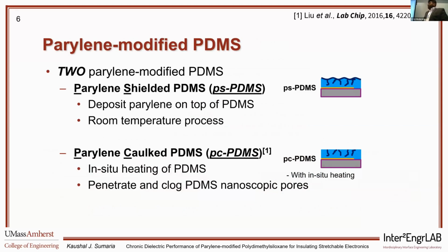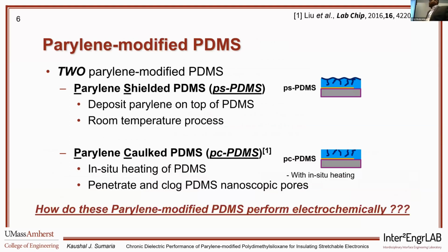One is the simple fabrication of sealing the PDMS with a layer of parylene deposited on top. Another one is a more complicated one where the parylene deposition is done at a higher temperature that expands the pores of PDMS and clogs the PDMS with parylene. So we test these two materials in the electrochemical systems and see how they behave when they are in the